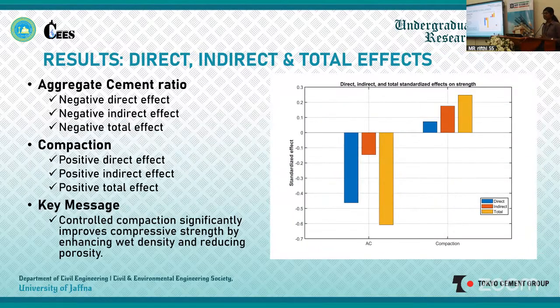The causal analysis shows a different influence for each variable. So the aggregate cement ratio produces the direct effect. In contrast, the compaction produces the positive effects. So the controlled compaction significantly improves the compressive strength by enhancing the wet density and reducing the excessive porosity.